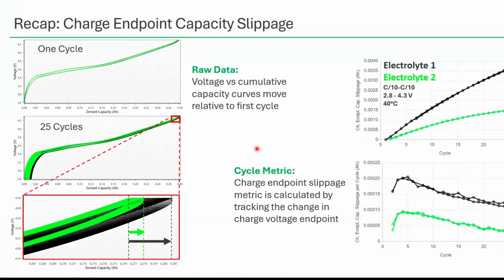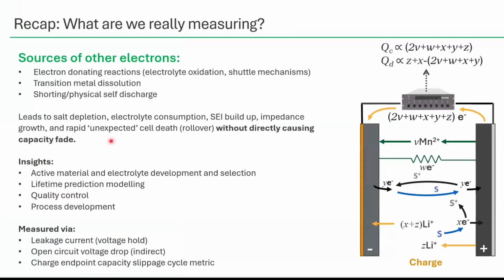This is how we calculate this charge endpoint capacity slippage. When we're charging and discharging a cell multiple times and looking at a cumulative capacity, instead of resetting the capacity to 0 every cycle, we just pick up and keep counting where our discharge ends off. So as we keep cycling, charging, and discharging, some of these excess electrons we count during charge end up making us walk a little bit further during charge than, say, the theoretical capacity of that cell.